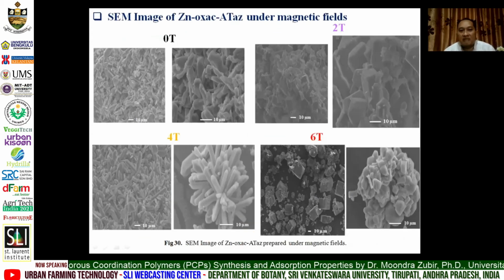And if we compare the same SEM image of this Zn-oxac-ATaz, the presence of the amine group induces an interesting morphology for its magnetic field crystal. This is the 0 Tesla magnetic field morphology, and then it changes at 2 Tesla. It looks like the particle size is increased compared to 0 Tesla. Then the 4 Tesla crystal, with significant change in the XRD pattern, also has a significant change of morphology. And then 6 Tesla looks like it makes a cubic shape, compared with the rectangular shape at 4 Tesla.